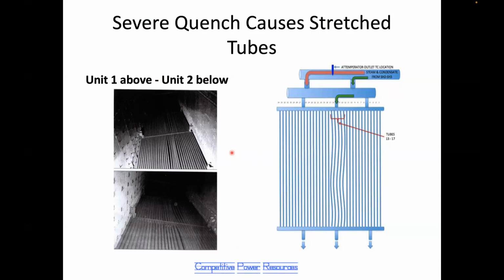All right. If you are passing water through a coil and you're quenching the tubes, one effect of that is to cause the cracking that we discussed and showed you pictures of earlier. Another symptom is the tubes that get quenched can be quenched so hard that they actually yield and stretch. And so when they come back to normal temperature, they're too long to fit in the space, and they do this S-shaped thing. This is a photograph of some stretched tubes. Here's another photograph of stretched tubes.